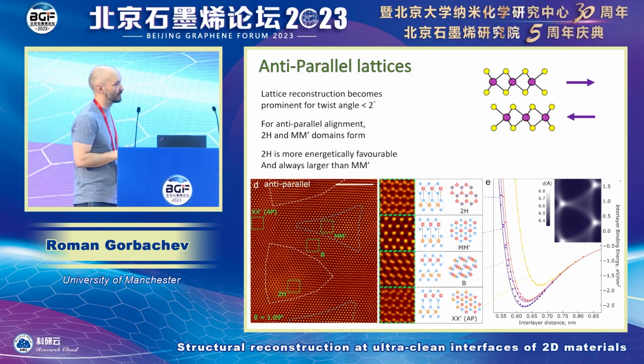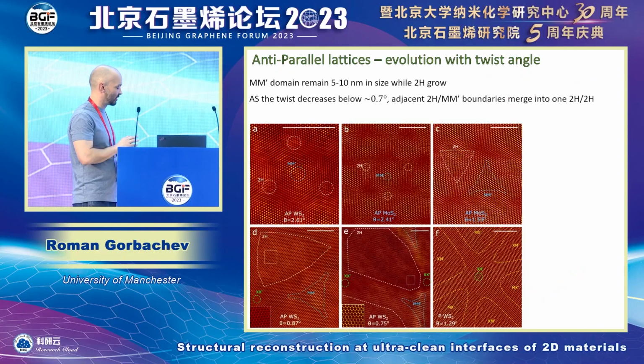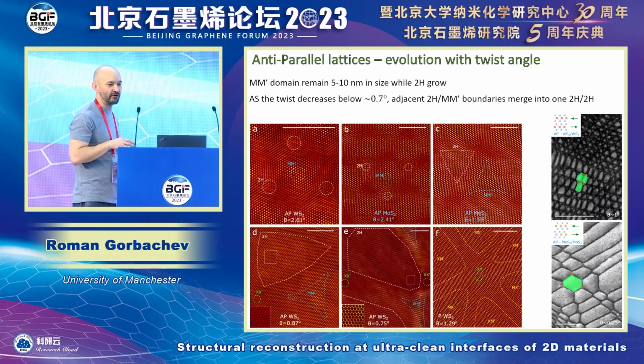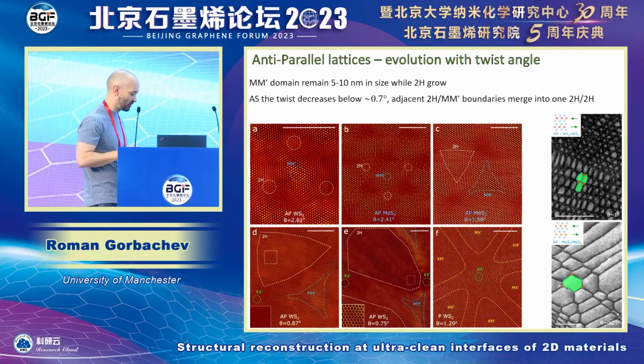So this is MM prime. It corresponds to the alignment of atoms in top and bottom layer. And this is the least favorable domain. And of course, there is this point here, which is unfavorable, and it doesn't form a domain at all. But what happens is that this kind of texture dramatically changes the properties of the system. And as you go from large twist angles to small twist angles, you can see that one of the domains expand. So you turn your system into bilayer, 2H bilayer TMD, but you have little grains of MM. And these little grains of MM at low temperatures form quantum dots. So what you create is a periodic network of quantum dots that are controllable. Their exchange and their interaction is controllable by the twist angle. And this is why it is such a flexible platform for exploration of quantum physics.